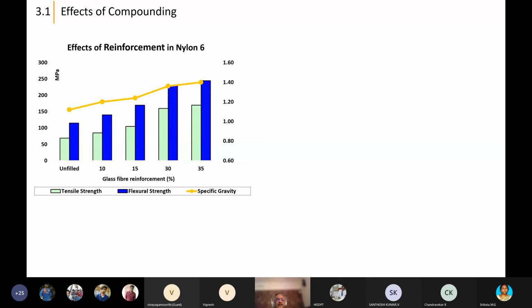You see the graph, there are two bars. One bar is tensile strength, light green. The dark blue is the flexural strength. The line shows the specific gravity. So when you increase the glass fiber from unfilled to 35%, what is the change? I have depicted the property for unfilled, then 10%, 15, 30, and 35. How the tensile and flexural properties go up, how the specific gravity also goes up. So this is the effect of different percentages of glass fiber on nylon 6.